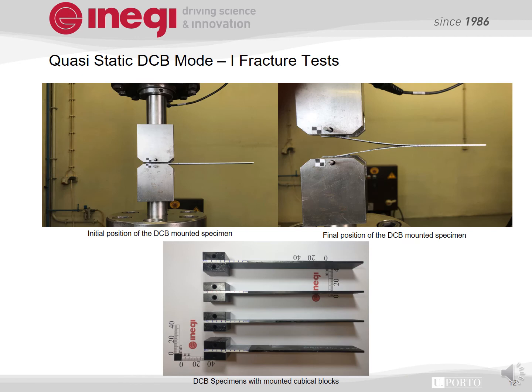Quasi-static DCB Mode 1 fracture test. These tests are conducted as per the standard ASTM D5528. The bottom image shows the DCB specimens mounted with the loading blocks, and these loading blocks are mounted on the testing machine with the help of pins. The first image shows the initial position of the DCB mounted specimen. The second image shows the final position of the DCB mounted specimen at the end of the test.